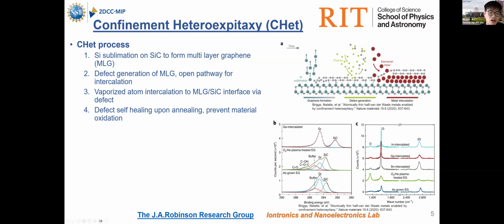As you can see in the schematic here, I would like to draw your attention to this. As we grow multilayer graphene on top of silicon carbide, the bottom layer, even though it has the graphene structure, doesn't really have the graphene properties because it is still bonded to the silicon carbide substrate. I will talk about that in more detail later. But as you intercalate the atoms, it will actually decouple the bonding between the bottom layer, which we call the buffer layer graphene, and the silicon carbide substrate. And then upon the atom intercalation, after we grow, the graphene will actually self-heal and preserve the intercalated atoms underneath the multilayer graphene from oxidation.